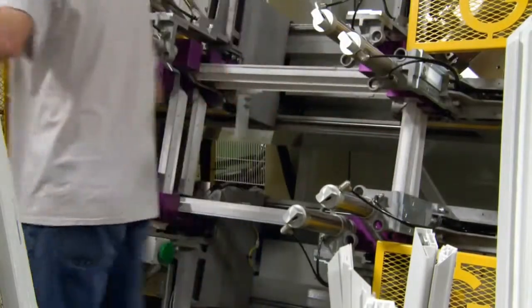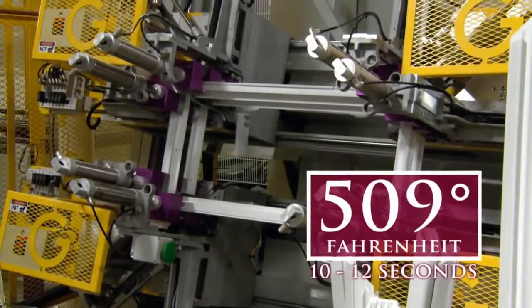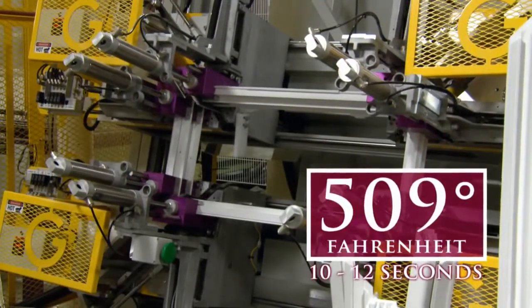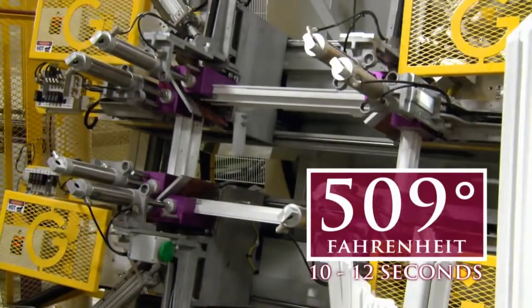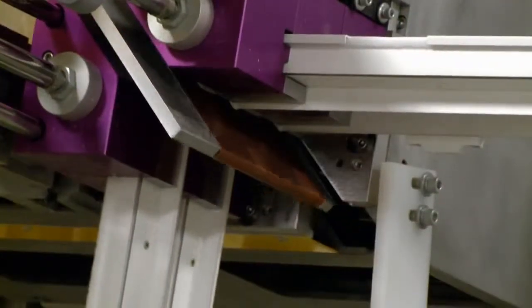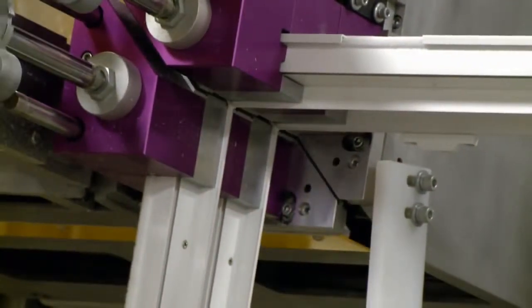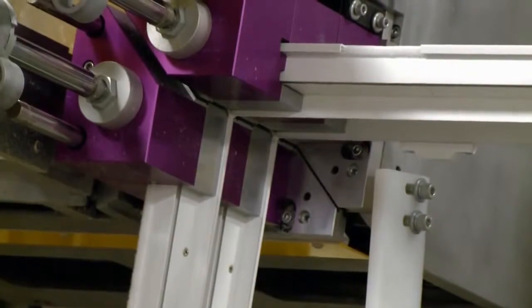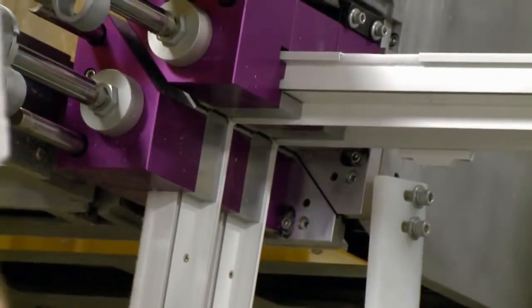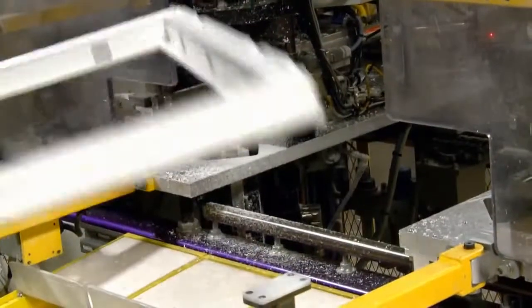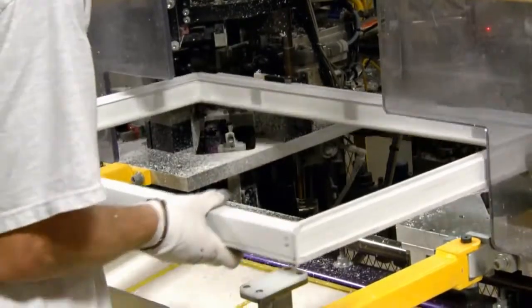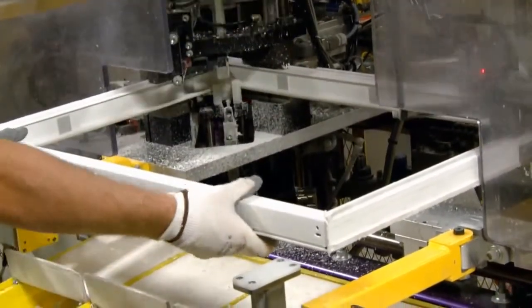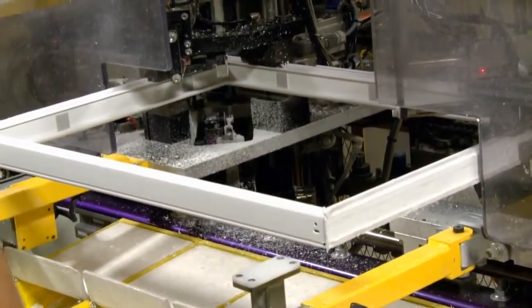The welders are set at 509 degrees Fahrenheit and the profiles are heated for around 10 to 12 seconds. As the heated Teflon-coated plates move out of the way, the profiles are then pressed together and given 10 to 12 seconds to cool. After this welding process, the burn-off is cleaned off the miter with special weld cleaners.